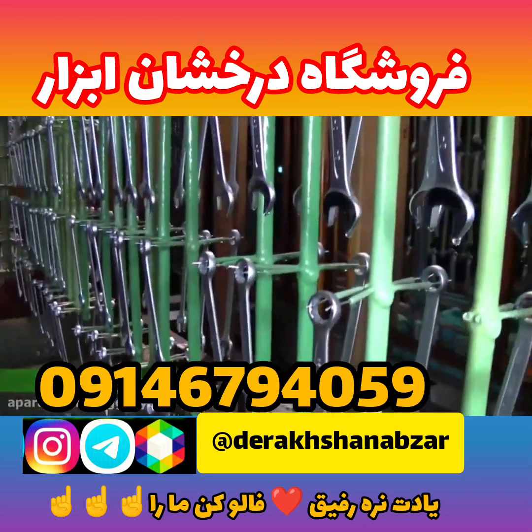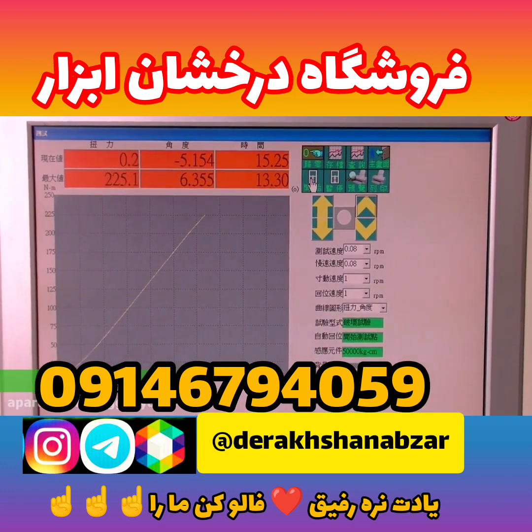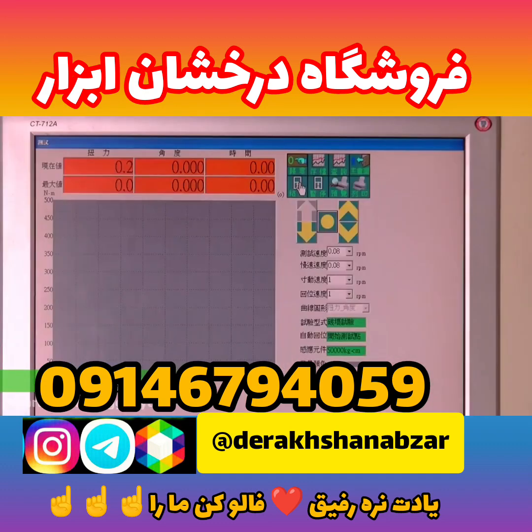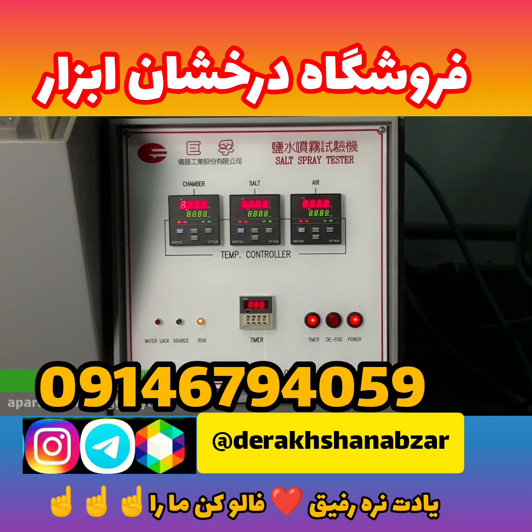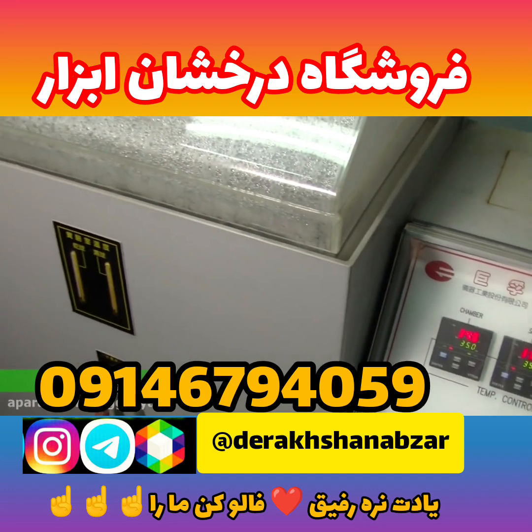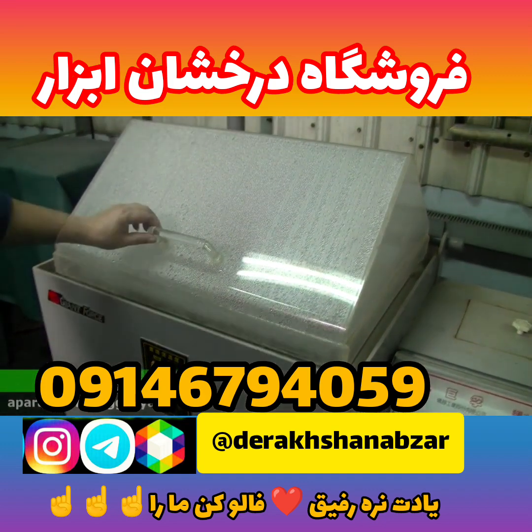Testing. The entire batch of finished products then goes through sample inspection by a Jonesway professional quality control engineer. The engineer will test the torque and hardness to ensure the finished product meets Jonesway's quality standards. After testing the torque and hardness, the Jonesway quality engineer examines the plating and corrosion resistance of the samples. The test samples will be mist-sprayed with atomized salt water for 48 consecutive hours. If the plating has been done correctly, the samples will not rust.